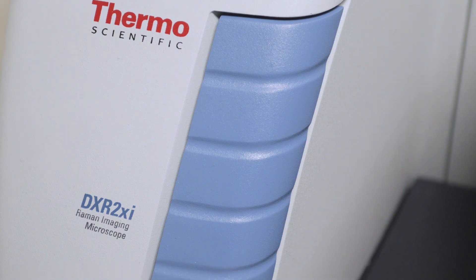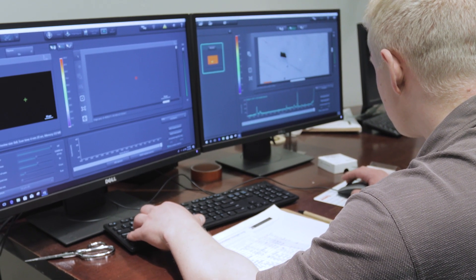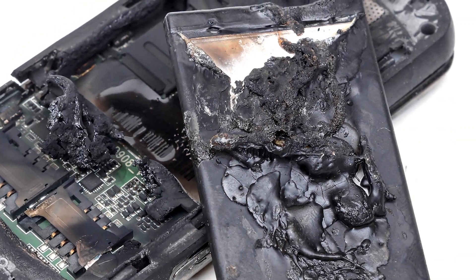We can also look at it from the point of view of what we call SEI layer formation — that's the solid electrolyte interface. The solid electrolyte interface is a very important aspect related to the safety of a lithium-ion battery, because it is the passivation layer which forms on an electrode surface preventing it from going haywire. Trying to understand how the electrolyte degrades as a function of cycling — all of that can be studied by Raman spectroscopy.